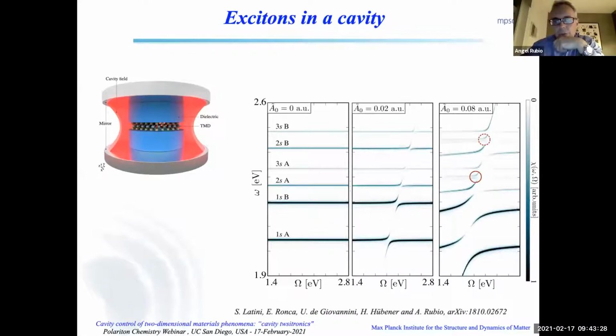Here we did include both the counter-rotating terms, and on top we did include the diamagnetic contribution, which is this electron self-polarization that has some effects to make the calculations stable. But you are perfectly right. You need to have this counter-rotating in order to transfer oscillator strength to the dark states.